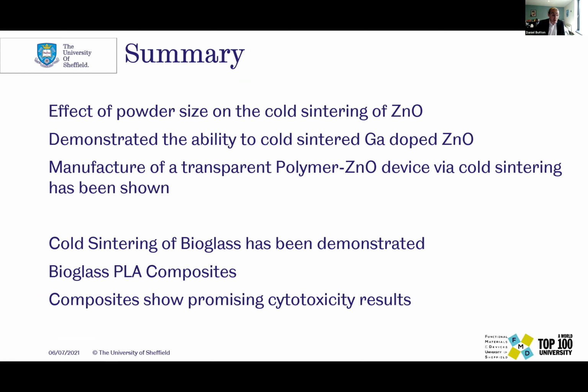So to summarize this quickly, I've gone over the effects of powder size and the effect of cold sintering of zinc oxide. Then I've talked about how we can introduce a dopant, gallium, if you want to introduce upscaling for the material into industry, and then shown the actual applications of cold sintering, and where we can produce devices which will be useful in applications of zinc oxide in cold sintering. And then Jess has taken us over bioglass, which is very important in biology applications and medical applications, and how we can combine them with PLA composites and the really good cytotoxic results we're having with the cold sintered material.